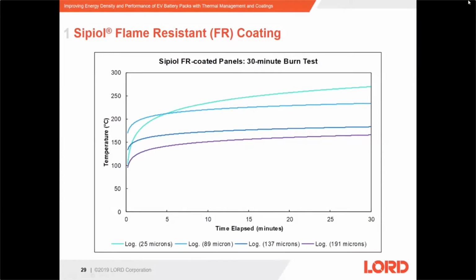This graph highlights only the Sipiol FR coated substrates from the previous slide to allow for more clarity for the performance at different thicknesses. In this graph, we used logarithmic trend lines to smooth out the appearance of the data. As expected, the thickest coating provided the greatest resistance to the burn test. But to reiterate, none of these trials exceeded the melting point of aluminum. The 25 micron coating maintained a temperature under 300 degrees Celsius, the 89 micron coating under 250 C, and the 137 and 191 micron coatings maintained temperatures under 200 degrees Celsius.